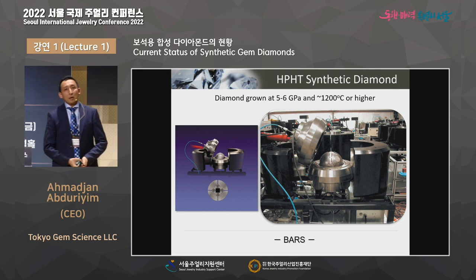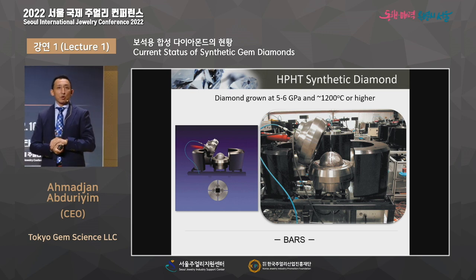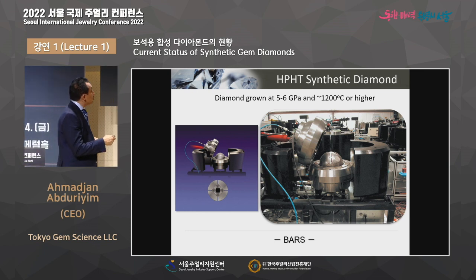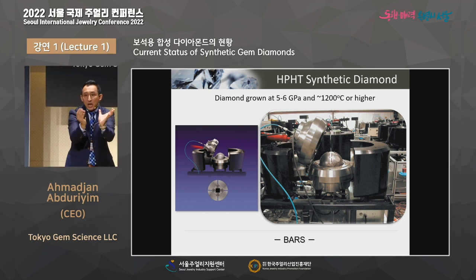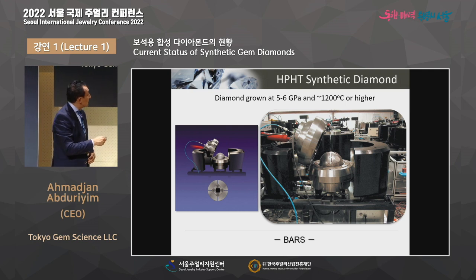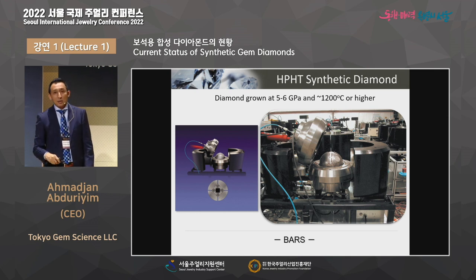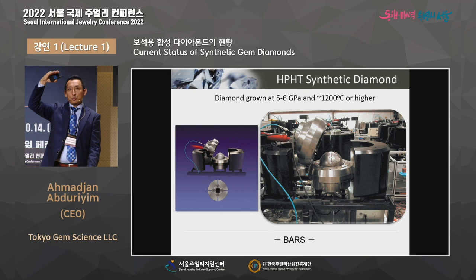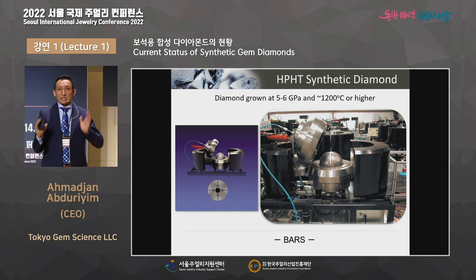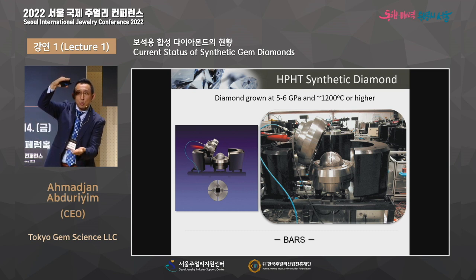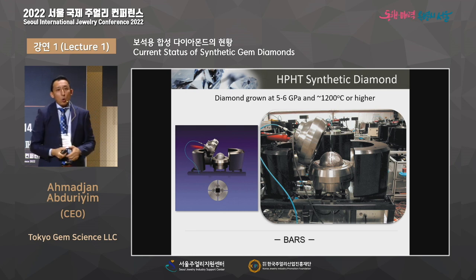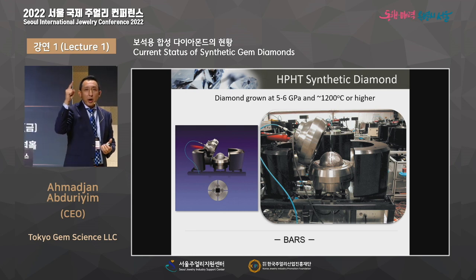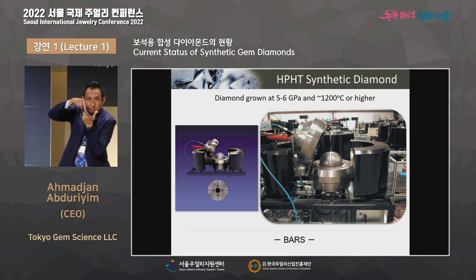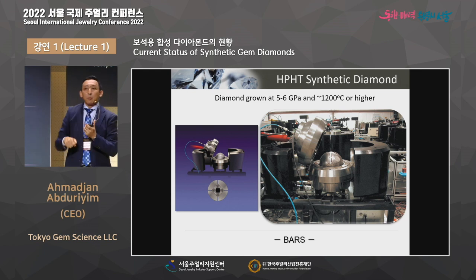And this is a much smaller instrument from Russia. It's a totally different shape from the Japanese one, and they show a more spherical shape with a cubic anvil inside, and they use 5 to 6 gigapascal. Do you know how high that pressure is? 5 to 6 gigapascal. You can never imagine that. Normally, it's like 150 kilometers of depth in the Earth, or just like one jumbo airplane put on your finger. This high pressure can create the diamond.